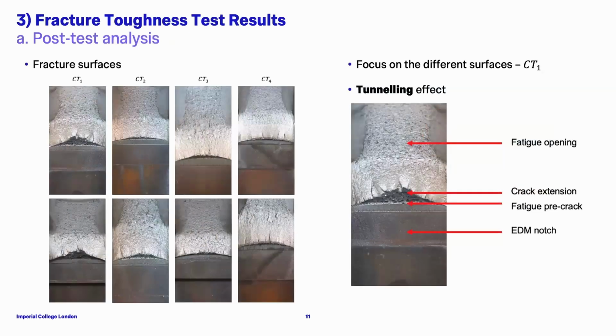I opened all my samples entirely by fatigue to analyze the fracture surfaces. And what I observed is that instead of having a straight line for the crack propagation, it was more about what we call a tunnelling effect.